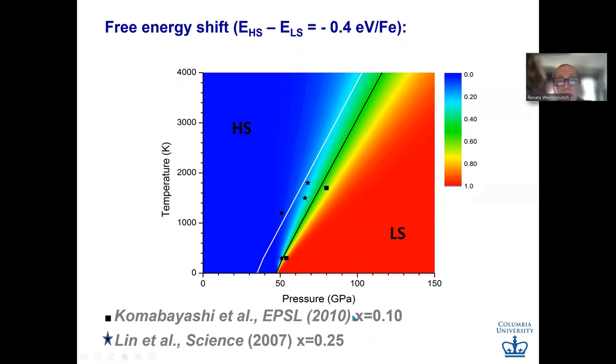In 2010, another experiment came up, and I'm going to go back to this because it is important too. This is the 2007 experiment, the STARS. And this is another experiment that came up in 2010 that's much more similar to our results, and that's for 10% iron. Up to 18% or 20% iron, things don't change very much. The phase diagram doesn't change very much. It's above 20% that things start changing. I didn't understand this at that time. I understand very clearly now.